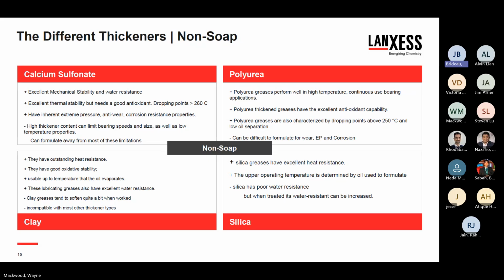They have very good high dropping points, good mechanical stability at high temperatures. These are typically the electric motor bearing greases of choice, and they definitely operate well at high temperatures. They generally don't have a lot of EP anti-wear. You have to formulate for that. And when you do formulate for that, unfortunately, the high temperature tends to fall off. So they still operate quite well, but what we would call the polyurea complex products, where you build in some EP and anti-wear, etc., are not as high an operating range as the pure polyurea products.